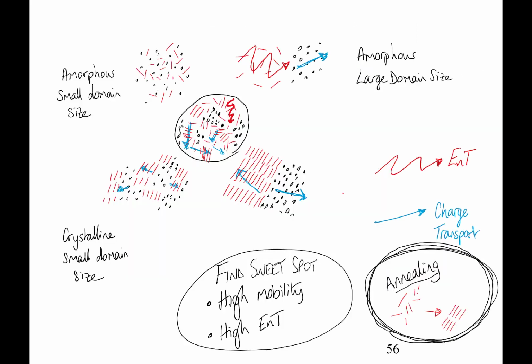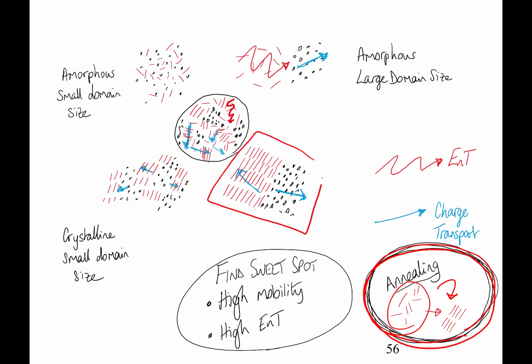So really what I'm saying in here, let's just come back to this image we've seen earlier. Annealing, what it does is it takes sort of amorphous, higgledy-piggledy oriented molecules and basically turns them into sort of more crystalline. But also we reach a point where we've actually phase separated. So we've separated here the fullerenes from the squaraines, and that's what annealing does for us in those cartoons.